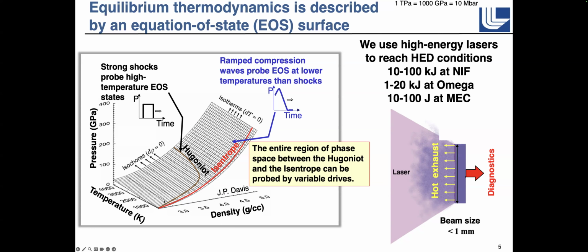The locus of points in this space for a single shock wave is the Hugoniot, and that gets very hot very rapidly. Well, rapidly in the sense of megabar pressures, and so this is where the HED designation comes about, because you continue to put more and more energy into the material, but you're getting so hot that you can't compress it anymore. So dynamically, if you want to compress to high densities, you need to follow something that's closer to the isentrope.